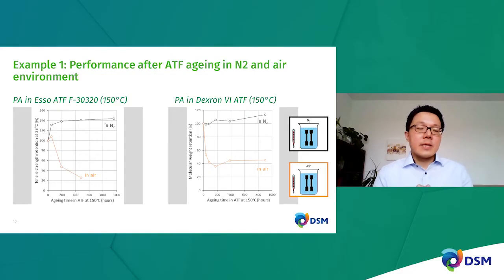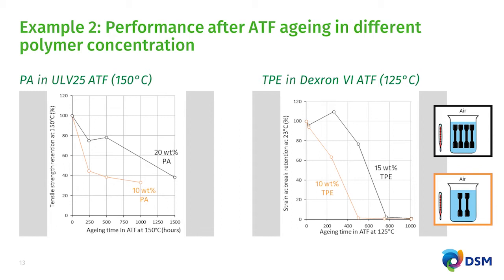The second example is something that is not that trivial. This is related to the relative amount of polymer that you use during aging. So the left-hand side figure highlights the tensile strength retention as a function of aging time of polymer in ATF at 150 degrees Celsius. In this case, I show two different cases where the black indicates 20% of polyamide, meaning that originally when you start doing this aging, you start with 20% polyamide and 80% ATF, versus the situation where you only use 10% of polyamide in the jar.